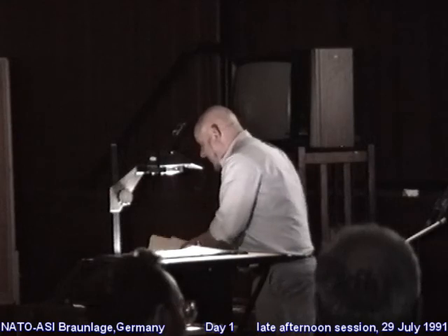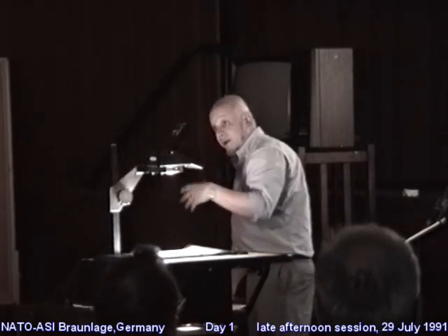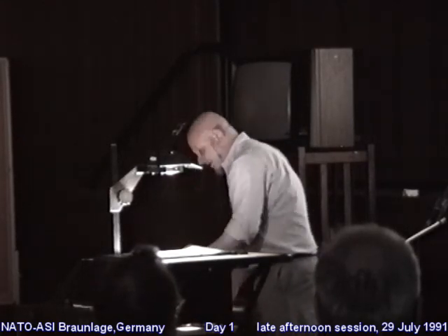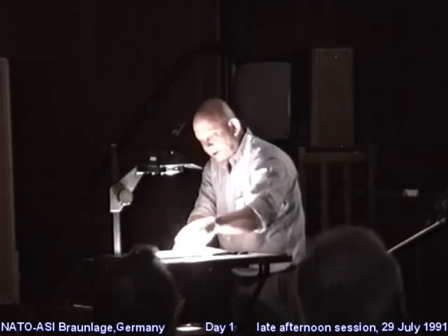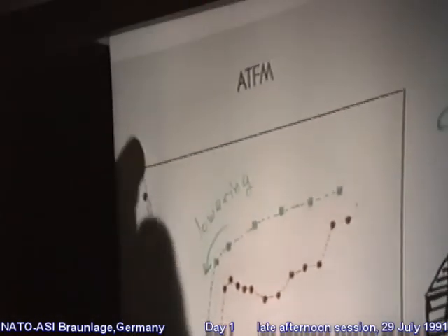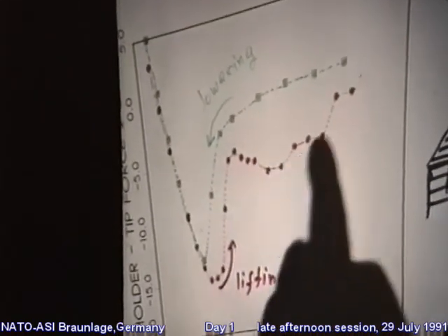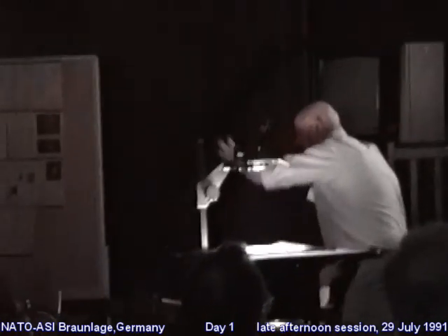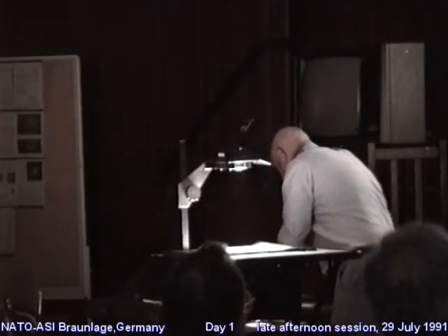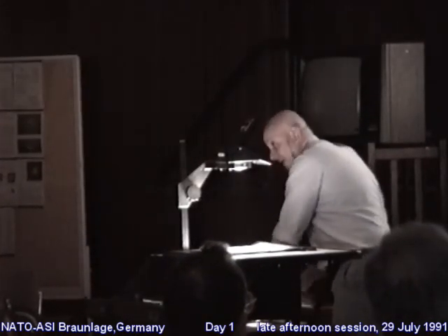We did these experiments with calcium fluoride. It does happen with this material. This is the hysteresis of calcium fluoride against calcium fluoride surface. Lowering, bringing it here to a repulsive force, and then lifting it, and you see hysteresis. Somewhat smaller than before. But then we did something else. We slid it across. And when you slide across, something very interesting happens.